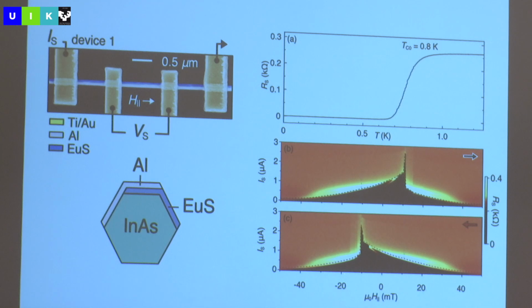And so we went back to our old game of putting the nanowires, only now there are these more complicated nanowires. The great thing is that we should be able to do this without any externally applied magnetic fields. So here's what things look like. Indium arsenide nanowire, there's gold contacts so that we can measure what we're doing, and aluminum and europium sulfide. And we've picked a particular interface configuration that looks like this. Now, you might not like that one. You might wish that something was on top of something else. And, okay, we picked this one. And the aluminum had to go on last. This was a problem: the aluminum had to be cold, but the europium sulfide didn't like being cold. So we had to put them on in this configuration. Anyway, this is what we did.